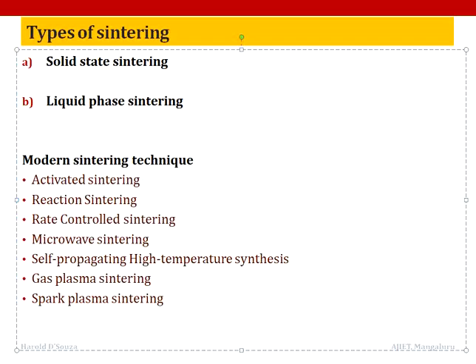Spark plasma sintering or SPS is a process similar to uniaxial pressing in which a momentary DC current pulse is generated in addition to the Joule heating. Now, by producing a spark between the powder particles, the temperature during the SPS can reach up to 5000 to 10,000 degrees centigrade, but only momentarily, so that no melting is allowed to take place. Functionally graded materials can be produced by this method.